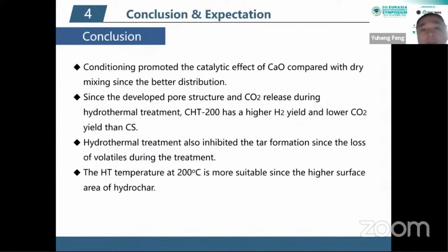So these are the conclusions. Firstly, the conditioning promoted the catalytic effect of calcium oxide compared with dry mixing, due to better distribution of the addition. Since the developed pore structure and the carbon dioxide releasing during the treatment, the CHT has a higher hydrogen yield and a lower carbon dioxide yield than CS. The hydrothermal treatment also inhibited tar formation due to the loss of volatiles during treatment.